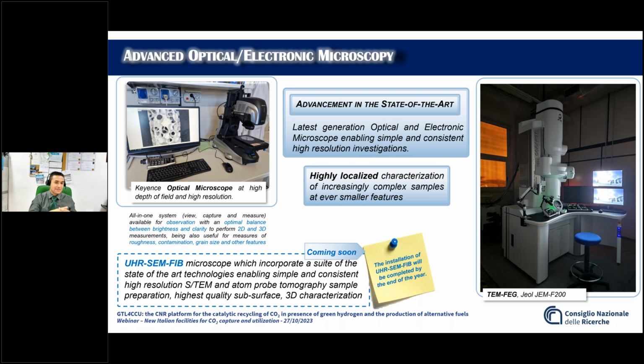However, our flagships are the transmission electron microscope field emission gun instrument, able to deliver a punctual resolution minor than 0.2 nanometer at 200 kilo electron volt without aberration correction. The instrument is already available and is working. Already it is in full service, and moreover we have also purchased an ultra-high resolution field emission scanning electron microscope equipped with the focused ion beam FIB source and detector STEM. This installation will likely be completed by the end of the year.